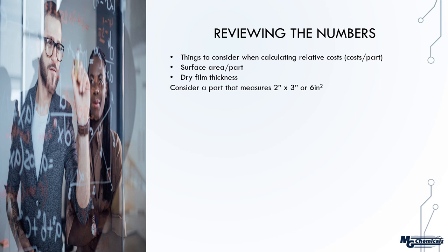So what we have to consider is getting down to how much each part costs to coat. To do that, we need to know the surface area of each part and the dry film thickness. Now, we give recommended dry film thicknesses, but at the end of the day, a customer is going to have their own process and methods, operator efficiency, that sort of thing. So dry film thickness averages out based on the user more than anything else, and they need to gauge what they expect in terms of dry film thickness. So let's, for example, consider a part measuring 2 inches by 3 inches to give us 6 square inches.